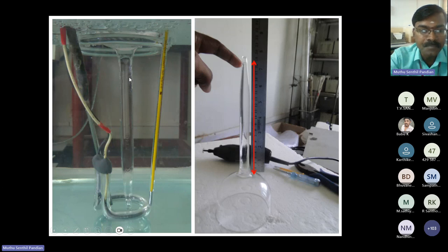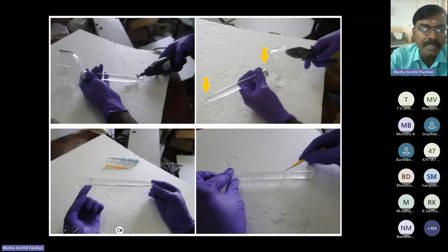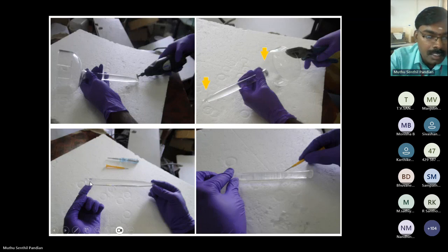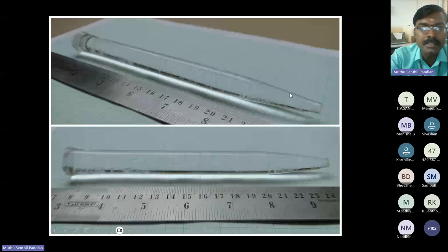So this is the entire crystal inside the glass sample, also inside the water bath. So this is the crystal inside the glass sample. So using this diamond wheel cutter, we have to remove the top and bottom portions separately. And this is the 25 centimeter longest TGS crystal along its polar b direction with the glass sample. And using the glass cutter, we have to remove the top and bottom portions separately. So this is the 25 centimeter longest TGS crystal without any glass sample.